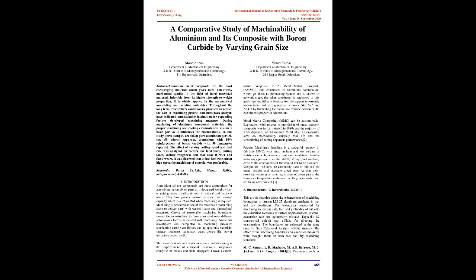machinability. In this study, 3 samples are taken: pure aluminium with particle size 50 micron, approximate, and aluminium with 10% reinforcement of boron carbide with 50 nanometer, approximate. The effect of varying cutting speed and feed rate was analyzed on factors like feed force, cutting force, surface roughness, and tool wear, crater and flank wear.